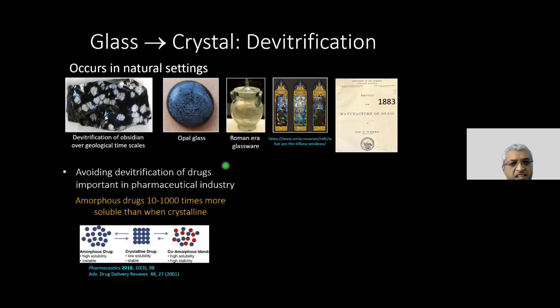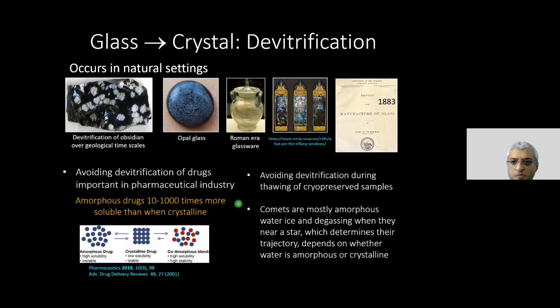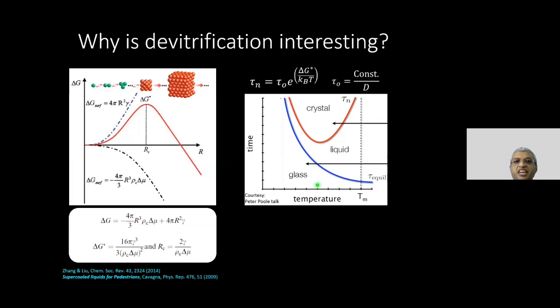So why is devitrification fascinating? The devitrification is fascinating because in the pharmaceutical industry, people want to make their drugs remain amorphous, because amorphous drugs dissolve about 10 to 1,000 times more easily than crystalline ones. So you want to maintain the glassy state of the drug. For example, when you do cryopreservation and you try to thaw the sample back to ambient temperature, the biggest hurdle right now is to avoid crystallization, because when you turn on crystallization, you produce these sharp spikes. The crystal grows in sharp facets and spikes, which tends to ruin the sample. And people also worry about it in the astrophysical context. Okay. Now, what's fascinating about devitrification compared to conventional crystallization is essentially the following.